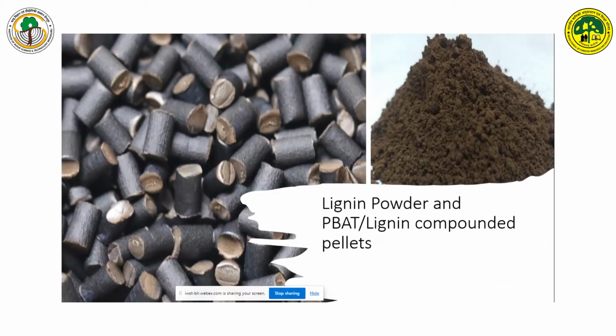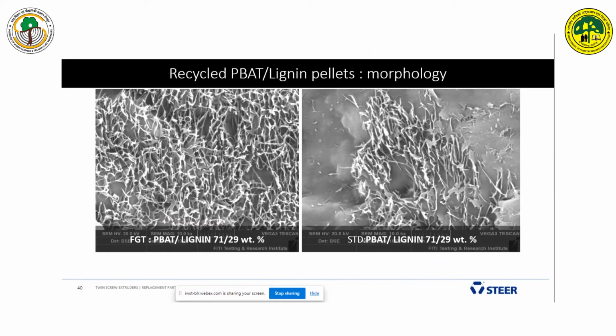This was the lignin powder, on the right hand side. After compounding lignin with the PBAT, the pellets look like this, and they were compact with better elongation. When we did the SEM study on the PBAT and lignin with 29% lignin and the remaining PBAT, we observed that the lignin at the top layer was completely distributed into the polymer matrix like PBAT. But in the case of standard technology, it was not completely distributed and the wetting was very poor, because I can still see the polymer, and the lignin was not homogeneously distributed in the standard technology. That could be the reason for the lower mechanical properties with standard technology.